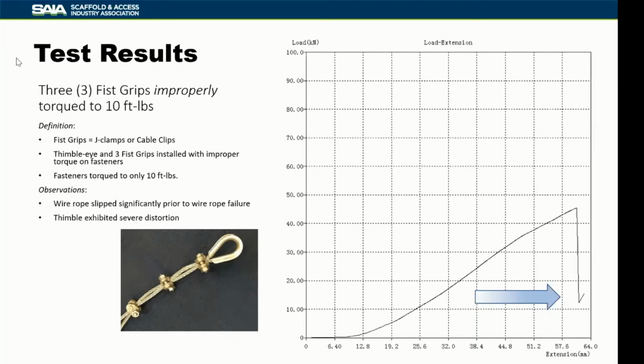The thimble actually showed severe deformation, and our breaking force was also significantly less than when we had fist grips that are properly torqued. You can see in terms of the elongation, we're clear out to almost 60 millimeters. We were at maybe 1.5 inches, and now we're up against 2 inches, maybe 2¼ inches of elongation.